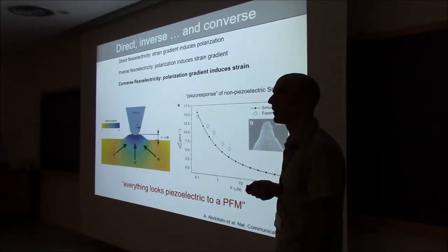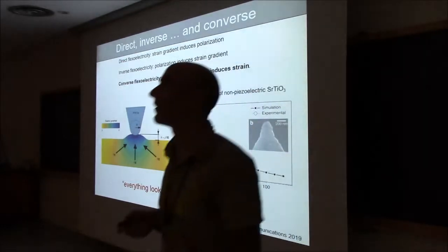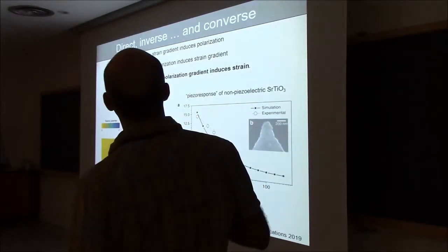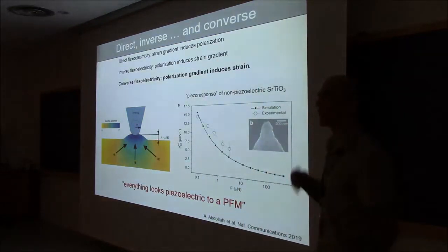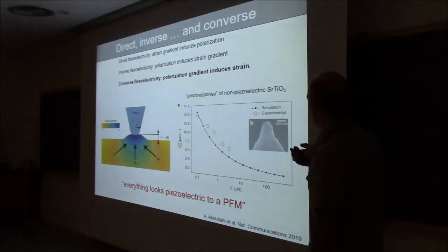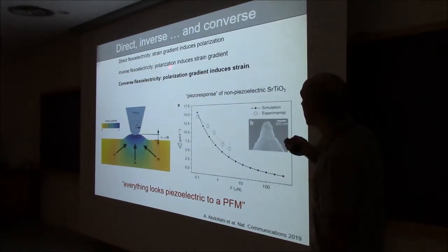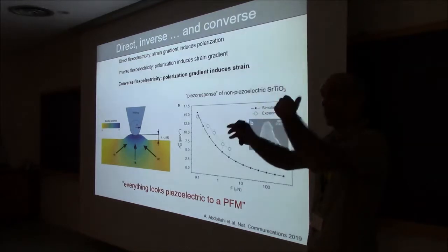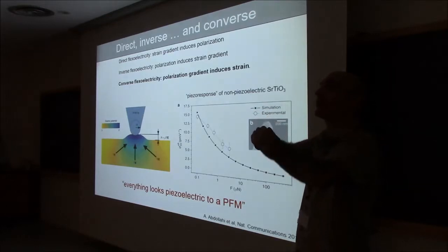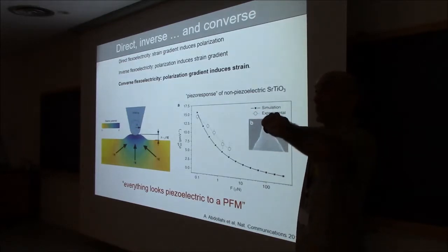Then you realize, how could you differentiate the inverse and converse one? How do you differentiate between inverse and converse? As I say, I think when you actually treat them theoretically, they boil down to the same thing. Physically, it's different. Here, I apply a homogeneous field. So you take a parallel plate capacitor, your STO substrate, and you apply a homogeneous electric field, and then you get, as a result, a strain gradient, as in, the crystal will bend.